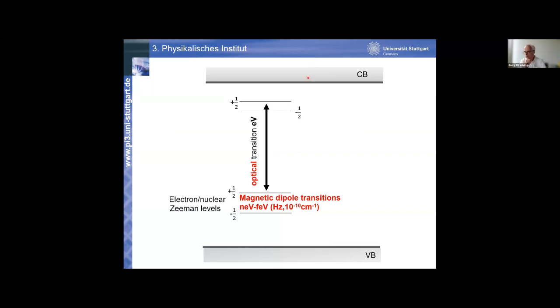If you dope that material, then you can generate optical two-level systems, that is, isolated energy levels within the band gap of that material. For the dopants we use, typically the energy separation between ground and first excited state is on the order of an electron volt. That is, optical transitions lie at around 600 nanometers or so. And we choose systems where we have a strong optical dipole transition, very much like we have in lots of atoms people use for atomic vapor magnetometers or optical clocks.